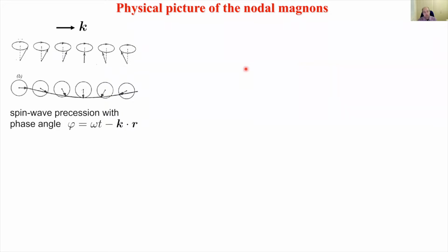So let's try and understand visually where this degeneracy comes about. And the magnon is a spin wave propagation where, if we consider here a representation with the equilibrium, all the spins were vertically up, then a spin wave means that we've taken a spin away from equilibrium, and then through exchange, this drags along all the neighboring spins, and then spins rotate both as a function of time and position with a phase, which is this projection transverse to the equilibrium direction.